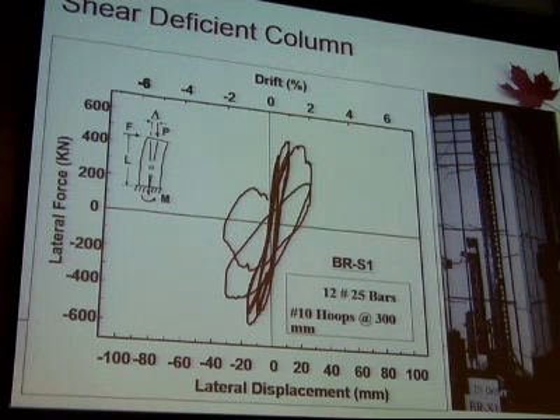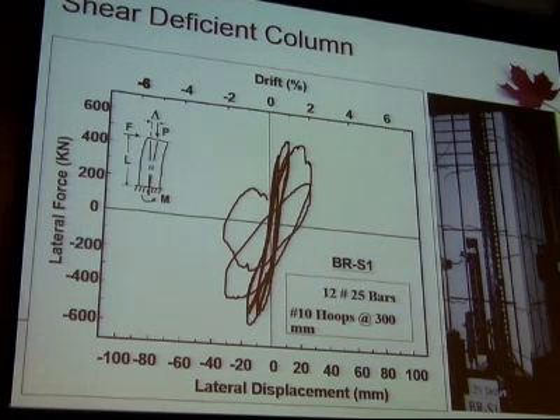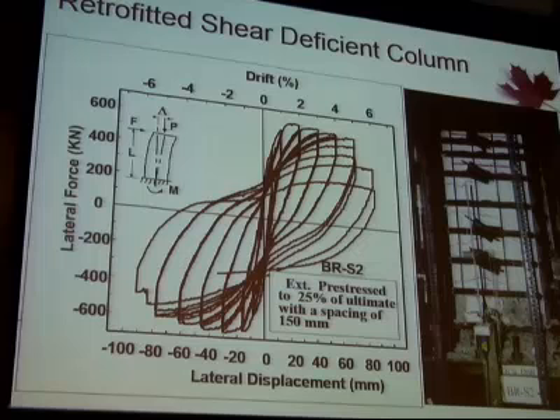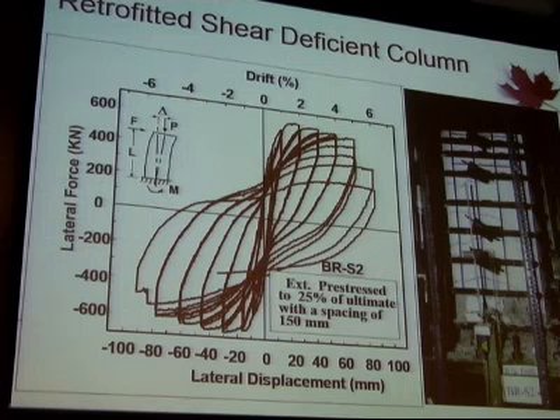Here you see a shear dominant bridge column, and typically shear dominant columns, if they do not have sufficient transverse reinforcement, cannot exceed 1% drift, which is not sufficient during earthquakes. But if you did apply this transverse pre-stressing, then you could go over 4% drift. And the level of pre-stressing depends on the type of performance you expect. If you want a crack-free column after a reasonable magnitude of earthquake, literally without any cracking, you can increase your transverse compression, which would overcome cracking of concrete.